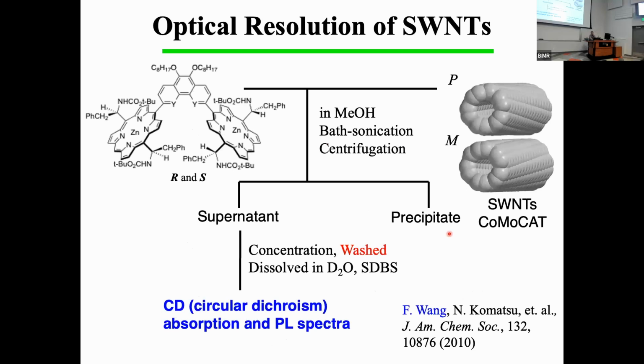And this is the experimental procedure, how to separate and extract the carbon nanotube. We just mix this host molecule and the single wall carbon nanotube in methanol with bath sonication, and after some time we centrifuge to separate the precipitate and the extract. We separate the supernatant, then concentrate and wash out this host molecule using pyridine or THF, an organic solvent, and dissolve the carbon nanotube in the presence of the surfactant SDBS in D2O, then measure the spectroscopies.